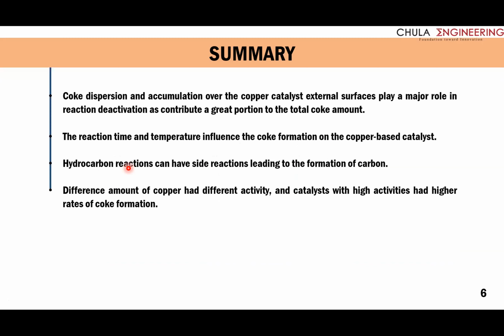This slide shows the summary. First, coke dispersion and accumulation over the copper catalyst external surface play a major role in reaction deactivation, as they contribute a great portion to the total coke amount. The second is the reaction time and temperature influence the coke formation on the copper-based catalyst. The third is hydrocarbon reaction can have side reaction leading to the formation of coke. The last one is that different amounts of copper have different activity, and catalyst with high activity has high